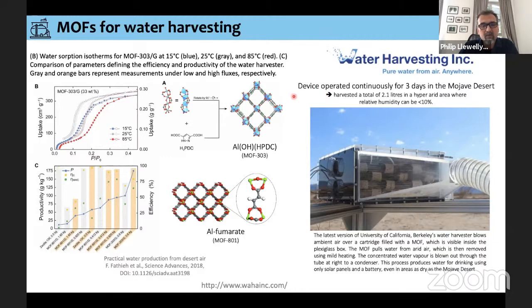Again, for the metal organic framework, if we look to the patents, or to some of their publications, we can see that this aluminium fumarate seems to be one of the materials they've been looking at. And this MOF-303, this material here, is a second MOF that they've been looking at. Here they've compared the productivity, here in blue, with respect to the efficiency, either under low flows or high flows. We can see that the efficiency for this material here, MOF-303, under high flows seems to be the best.